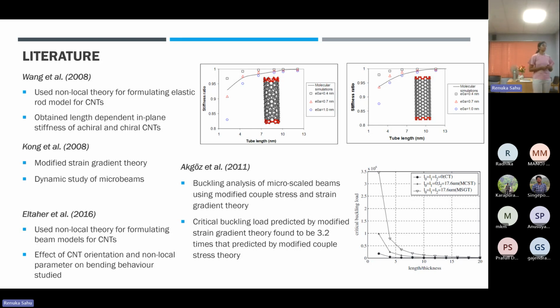Further, by using modified couple stress and strain gradient theory, the buckling analysis of microscale beams has been done, wherein the critical buckling load predicted by modified strain gradient theory was found to be 3.2 times that predicted by the modified coupled stress theory, which is again higher than what we get in the normal classical approach. This shows that we need to modify our existing theories for micro and nano-based structures.